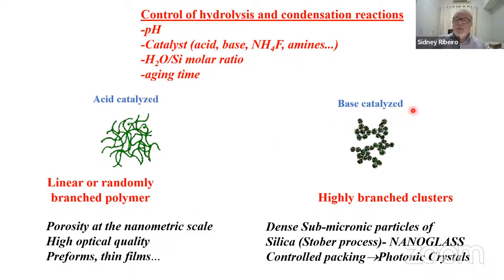On the other side, if you use base-catalyzed processes, you will have highly branched clusters. It means that we will have particles, in general submicronic particles of silica. This is the so-called Stöber process. And these particles are in fact called in the literature nanoglasses. If we control the packing, for example, we can get to photonic crystals.